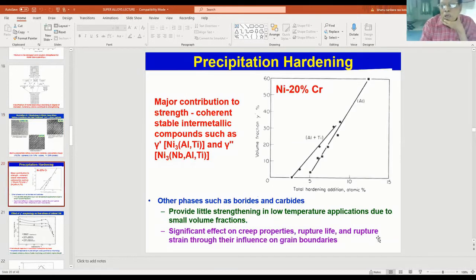You see how much aluminum has to be added in order to reach a given volume fraction of gamma prime, versus total hardening addition in atomic percent. For aluminum, you have to add so much aluminum in order to give you the Ni3Al precipitates. When we add titanium, you don't need that much aluminum. So aluminum and titanium function similarly. So Ni3(Al,Ti) is the phase which is forming there. And similarly, Ni3Nb, with aluminum, titanium, and other things will form.